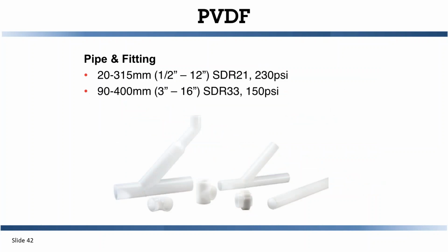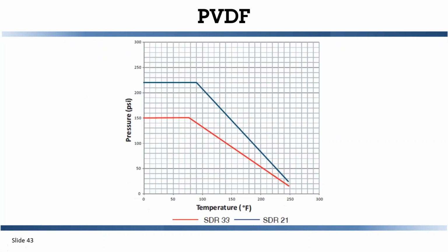PVDF, the first fluoropolymer we'll talk about, has two SDRs available. It is SDR21, has a 230 psi pressure rating, and then SDR33 has 150 psi pressure rating. So a little bit higher than the polyolefins and with a thinner wall. The higher the SDR number, the thinner the wall. Pressure temperature chart. Limiting factor of 250, we approach 30, 40 psi depending on the system.